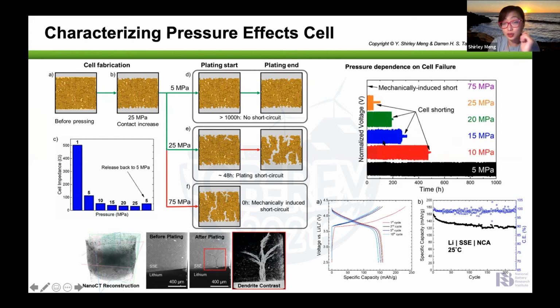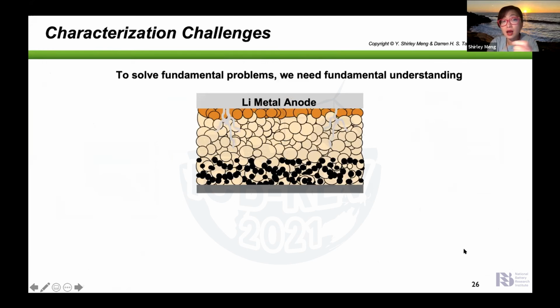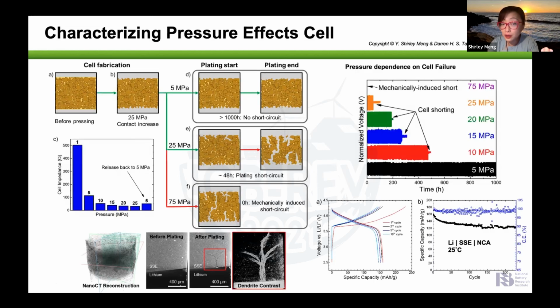And the trick is really when you cycle the battery. When you make the battery, you need high contact pressure. But when you cycle the lithium metal battery, you need to release the pressure. So when the pressure goes below 5 megapascal, you can then, at a low critical current density, very well cycle the lithium solid-state batteries.